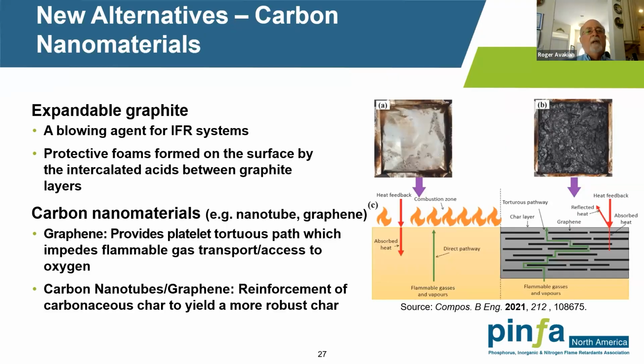One that's been around for a while is expandable graphite, again based on carbon. This is typically graphite that's been intercalated with a strong acid, typically sulfuric acid. And then the excess sulfuric acid is washed away. So you have this black compound. And it's an excellent material, because when it is heated up, it expands greatly. I mean, typically 200, maybe even 300 to 400 times its volume. So in other words, in a thin coating, you'll have a material that's going to expand to several millimeters, if not even a centimeter.